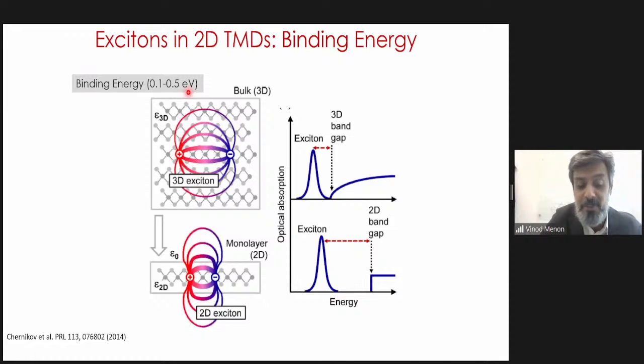Just to give you again a feel for the numbers, gallium arsenide, which is one of the most widely used semiconductors, the binding energy is in the tens of milli electron volts. So almost an order of magnitude smaller or even less. The result of this is that the exciton is very well separated from the quasi-particle band.